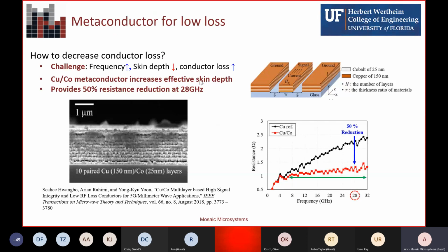And I forgot I included this. This is sort of researchy, but actually quite interesting, and it's an active program that we're doing with the University of Florida. The idea here is to take low loss glass, fused silica, and University of Florida's low loss metaconductor technology, and apply them together to make ultra low loss, in this case, radar arrays. The University of Florida has a copper cobalt metaconductor that basically reduces your conductor losses by 50%. And so we're looking to apply this into a glass-based technology for a very low loss compact radar array for autonomous vehicles, for example.